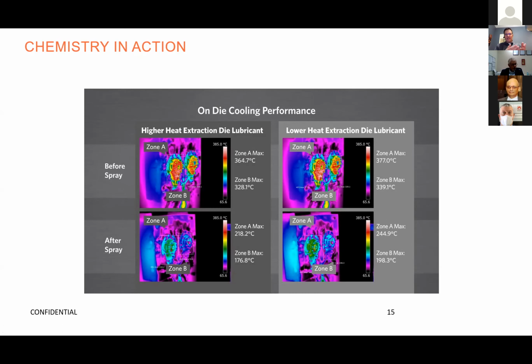Once again, the entire die cast process is thermal balance, going up and down. There's a paper yesterday that talked about spray and minimal spray, cutting down spray. If we think about it, every time you cool that die with die lube and then eject another part, it's going up and down so much, you get a lot of compression, a lot of tensile stresses on your tooling steel. And what's that lead to? It leads to your cracks, your heat check. That's where the damage to your die comes.